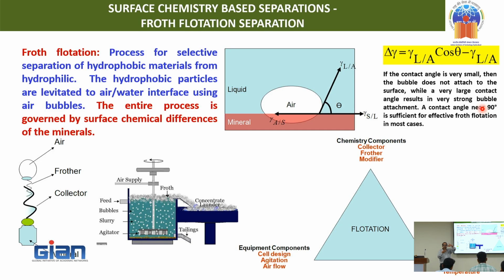So that will help the tail of the hydrophobic chain interact with the hydrophobic part of the collector, and helps in levitating to the surface, because the air bubble moves to the surface by the buoyancy force. Therefore, the hydrophobic mineral particle is brought to the air-water interface.